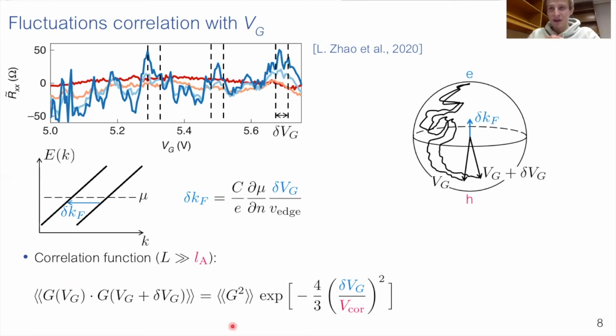The correlation function depends on the difference of gate voltages in a Gaussian way. And the correlation scale here, which basically determines the scale at which the signals are correlated, is determined by the following expression. Again, here are some prefactors like the capacitance to the gate and also the compressibility. But what's important is the dependence on the length of the proximitized segment and on the Andreev length.